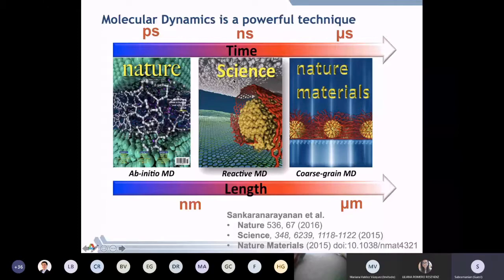And we used MD to actually trace the origin of why this effect is observed and to design these solid lubricants. And we've also used coarse-grained MD to design these nanoscale membranes and highlighted how there is a small asymmetry in the ligand distribution when these membranes form at an air-water interface. And that has interesting implications for the mechanical properties of these membranes. So those are the things that we have done, where we have individually used these different flavors of molecular